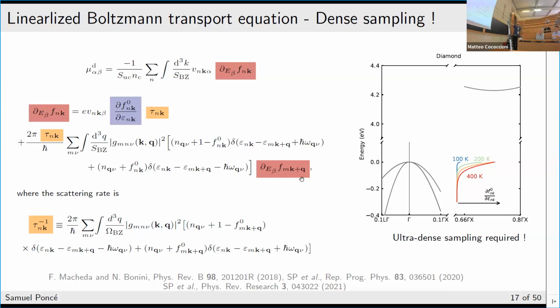So you can do approximation. Instead of computing this object that's quite difficult at a higher level of theory, you can simply plug in better phonon dispersion or better electron dispersion. This is actually easy to do in EPW. Instead of the Kohn-Sham states, you can put in GW states. There is an input flag to read external eigenvalues, and so you can compute all of this at a GW level, but you're only changing the E. It's not fully consistent because the G will still be at the DFPT level, but you can update the eigenstate. And in principle, you can also update the phonons.